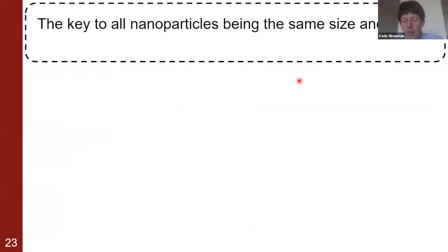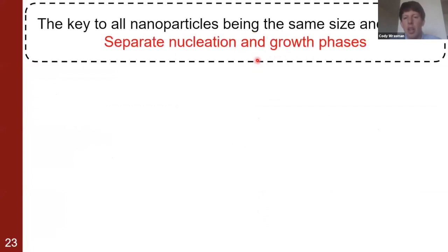And this is where one of the most important features of nanoparticle synthesis happens, and that's trying to separate these two phases of nanoparticle synthesis called nucleation and growth. If you're able to separate these two processes, you'll get very, very uniform nanoparticles. And as I mentioned, since nanoparticle size and shape are important for catalytic activity, it's important to get only one shape and one size of nanoparticles out of these synthesis processes so we can really understand what features are important for whatever catalytic reaction we're testing.